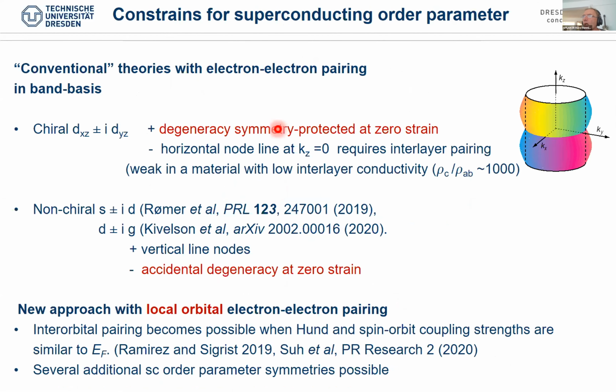Yeah, what are the consequences for the superconducting order parameter? Well, indeed, we think this experimentally proves that we remove a degeneracy between two superconducting order parameter symmetries with the strain. And one possibility to reconcile this with spin singlet superconductivity is actually the chiral dxz plus minus i dyz order, which was already discussed by Clifford an hour ago. It has some problems, in that it has this horizontal line node here. There are other cases of accidental degeneracy states, so s plus minus id or d plus minus ig.